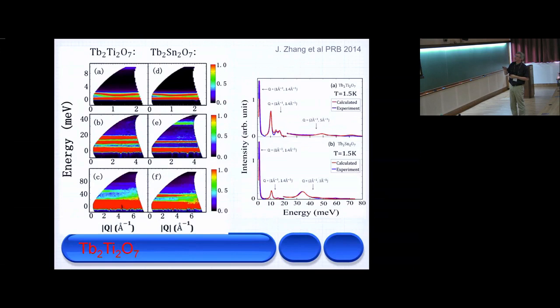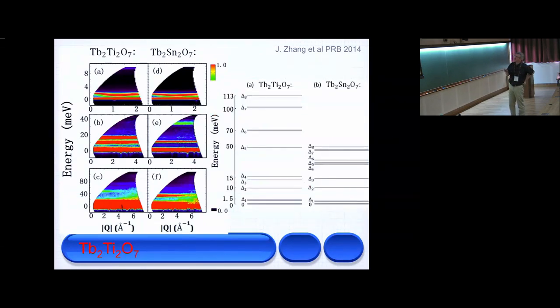And this is the titanate and stannate again, where there's a small difference in lattice parameter, but very little else. But from the calculations and the modeling of these data with heat capacity, you see that terbium titanate's crystal fields, its 13 levels, cover 120 meV, whereas in the stannate, everything is still significantly compressed down into like the first 50. This, as I said, remains a spin liquid, and this has an ordering temperature just below 1 Kelvin.